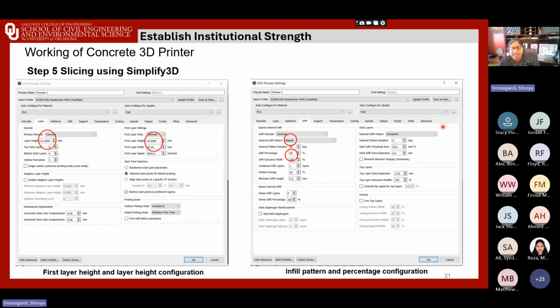So here we define the layer height. We are looking at about 11 millimeters, and this was also tuned to balance shape, stability, and also time because our mix is also setting. So too thin and just lapse of printing, all that weakens the print layers again. So we slowed down the first layer. We make sure of the adhesion and that there is no collapse of the building layers on top of it. So there was a strategy we had to learn.